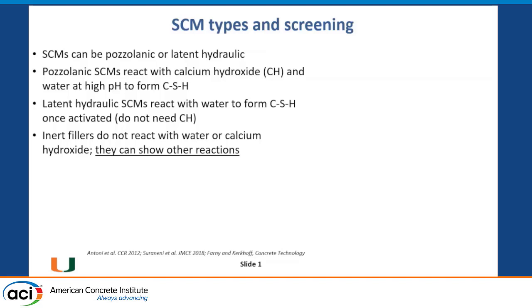There could be other reaction products as well. The primary difference between pozzolanic and latent hydraulic SCMs is the presence of calcium. There are also inert fillers, which are typically not considered supplementary cementitious materials — these do not, to a large extent, react with water or calcium hydroxide, though they can show other reactions to a small extent. Very typical examples: a pozzolanic SCM would be silica fume, latent hydraulic would be slag, and an inert filler would be limestone.